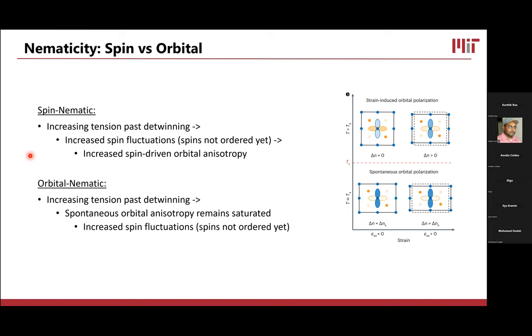I showed you that NMR paper earlier. If the spins aren't ordered yet, then increasing the lattice orthorhombicity should encourage them to get closer towards ordering, and it should increase the spin fluctuations. If the orbital anisotropy were only driven by the spin fluctuations, then I would expect the orbital anisotropy to also increase as I apply strain past full detwinning. That is not what we saw here. What we saw instead is that as we increase tension past full detwinning, the spontaneous orbital anisotropy remains saturated.